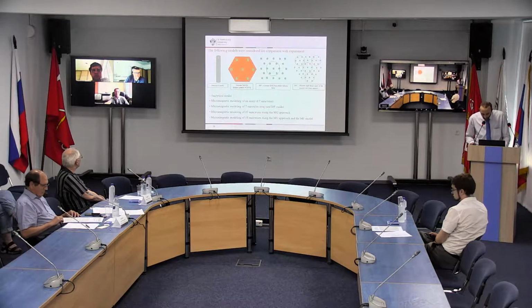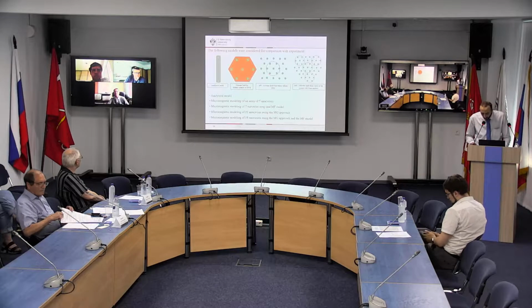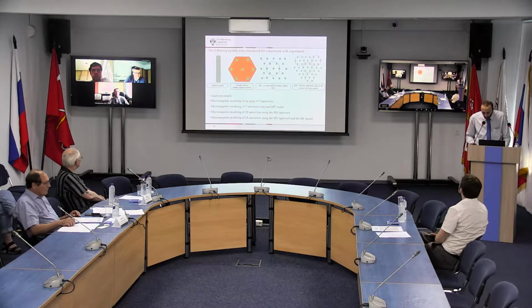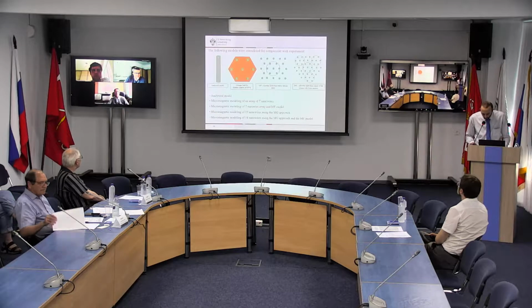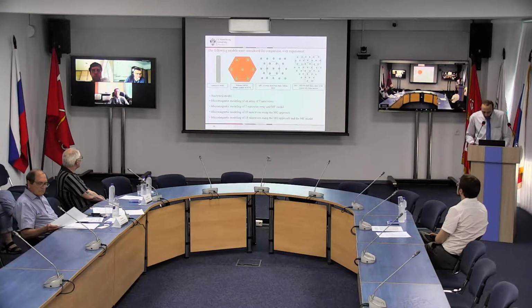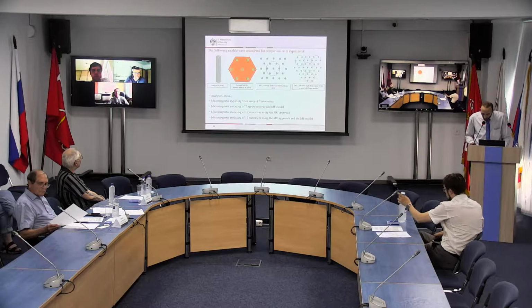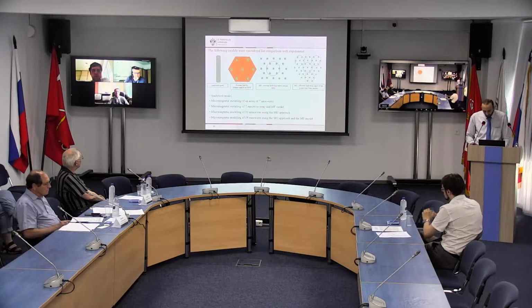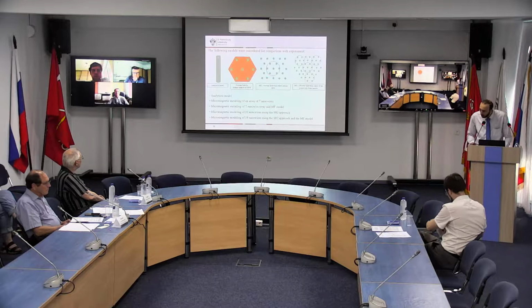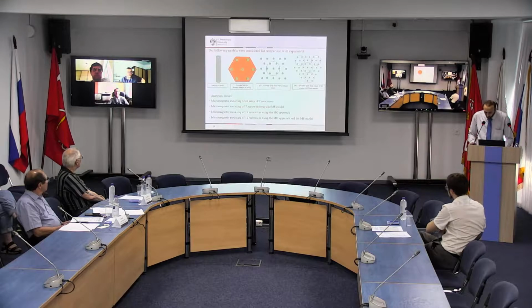The first model is the analytical model, which is built on a long nanowire with two separate magnetic charges on both the top and bottom of the wires. While a micromagnetic model calculates the average field from a definite number of nanowires. In our case, there are 7 nanowires. And a micromagnetic model with mean field approximation calculates the average field from the whole infinite array. On the other side, for the micromagnetic model using macrogeometric approximation, the effective field from copies of the system with a finite number is calculated.